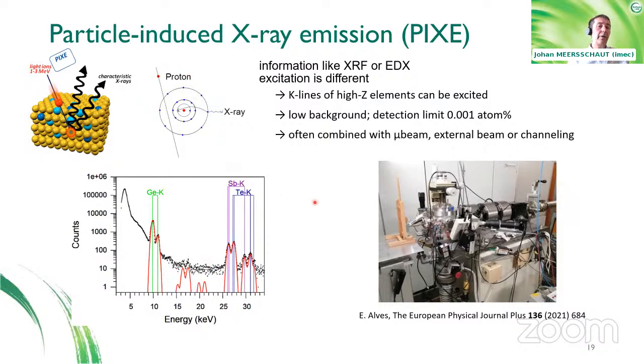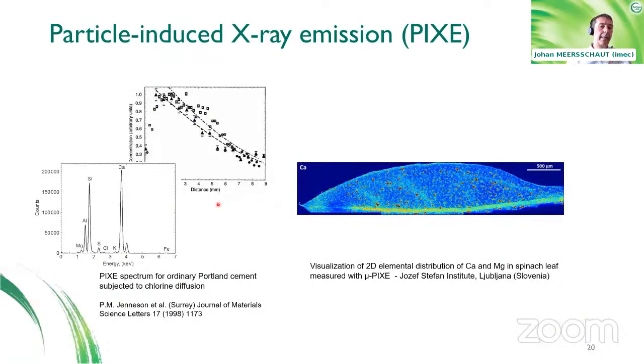And the second advantage of PIXE is that, given that the energies of the incoming protons are very high, you are also capable of exciting very high K-line energies. And that is why we are capable with PIXE to analyze high Z materials with proton-induced X-ray emission. And this technique is often combined with microprobes to characterize the material depending on the location.